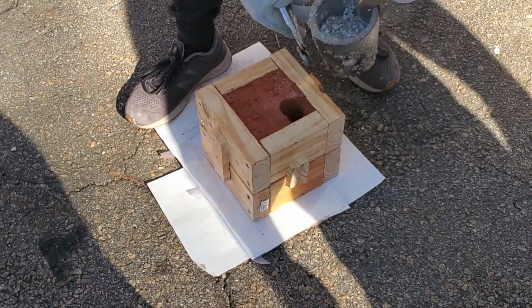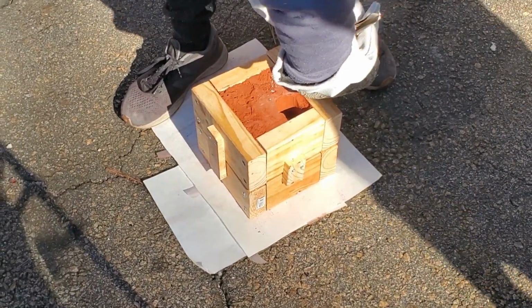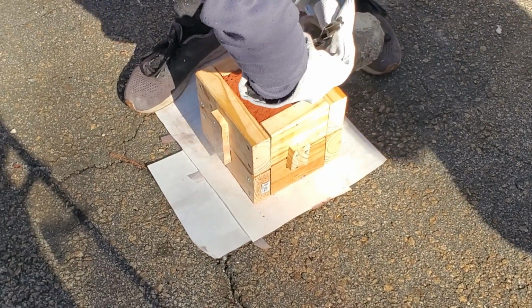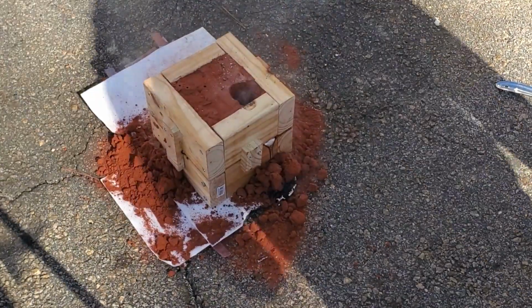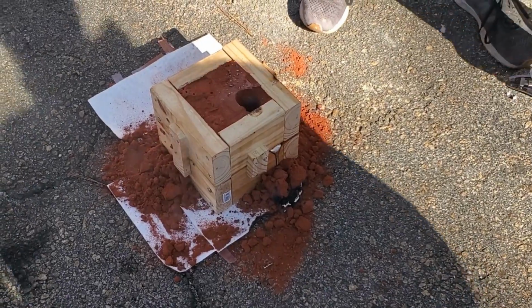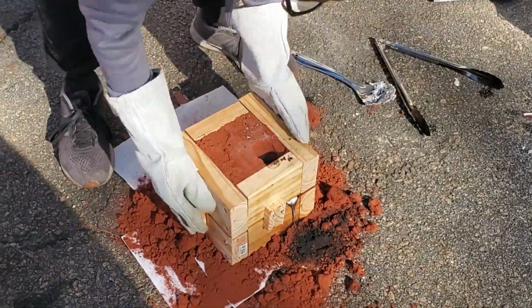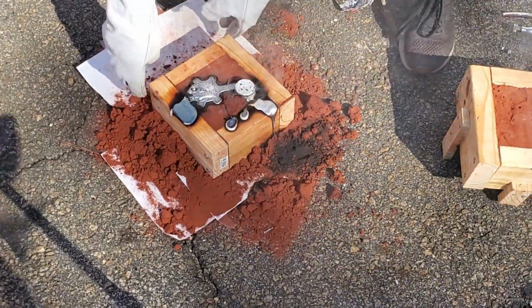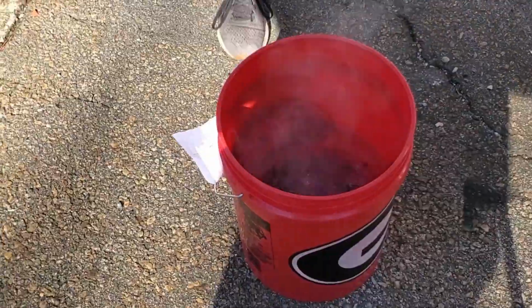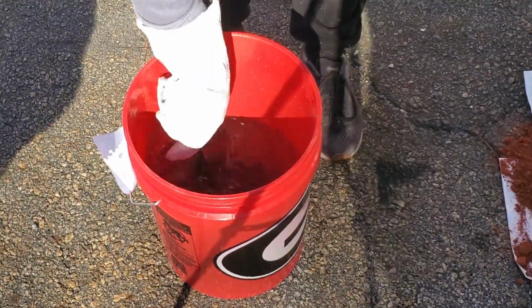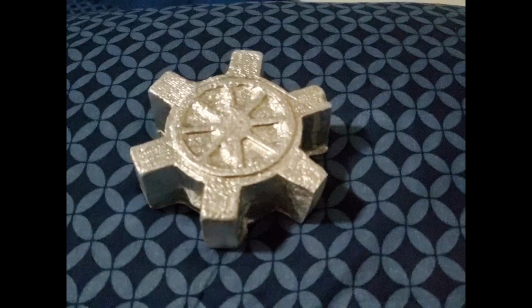While pouring the aluminum into our mold, molten aluminum started coming out of the parting plane. In order to prevent a metal fire, we placed sand around our mold as soon as we saw the aluminum coming out of our mold. After letting the part sit in the mold for a few minutes, we pulled it out and then placed it in water to help it cool faster. After cutting the excess aluminum off, this is what our final product looked like. For our first attempt, it turned out very well.